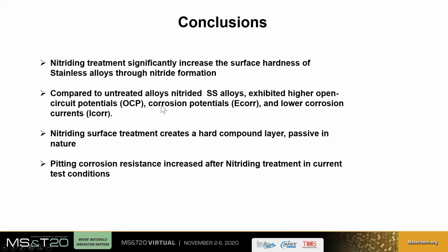At the end of the talk, I would like to conclude my study: nitriding treatment significantly increases the surface hardness of stainless steel alloys through nitride formation. Compared to untreated alloys, nitrided stainless steel exhibits higher open circuit potential and corrosion potential and low corrosion current. Nitriding surface treatment creates a hard compound layer, which is passive in nature, and pitting corrosion resistance increased after nitriding treatment in the current test conditions.